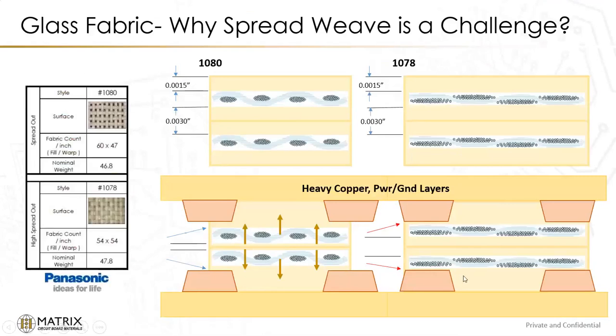And then the other part of it has to do with there could be voids in the side where the spread glass, because we're not able to take advantage as much of the resin. In the old days, it was more plies of 106, more plies of 1080, because those weaves are so open with that. And like Bob was saying, there's a lot of resin available by multiple plies, but that's really predicated on the fact that it could actually get through those gaps and get into the areas that are high pressure. So it's not necessarily the case with the spread glass, so you have to keep that in mind with it.